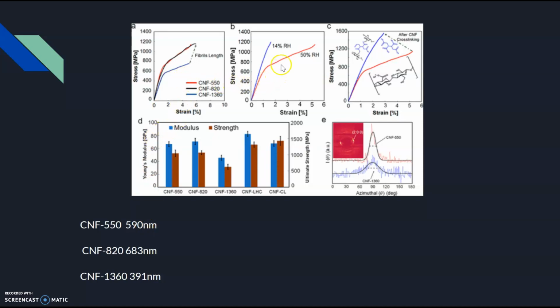It's another one, where RH just represents relative humidity. So they did more tests comparing it with humidity. And then lastly, the one they chose to demonstrate over here was the comparison with cross-linking. It demonstrated that the CNF cross-linking actually produces much stronger ultimate tensile strength in the material. And this letter D over here shows the comparison between the Young's modulus and the ultimate tensile strength of all the ones that were tested.